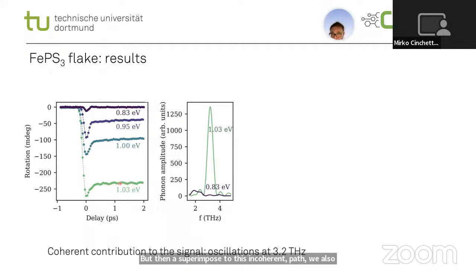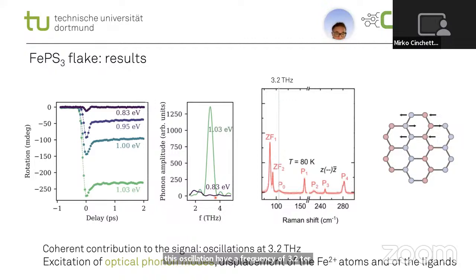If we do the Fourier transformation, we see that these oscillations have a frequency of 3.2 terahertz. If we have a look at the Raman spectra, we see that this frequency corresponds to an optical phonon mode, where basically the iron 2+ atoms and the ligands are displaced as shown in the figure here.